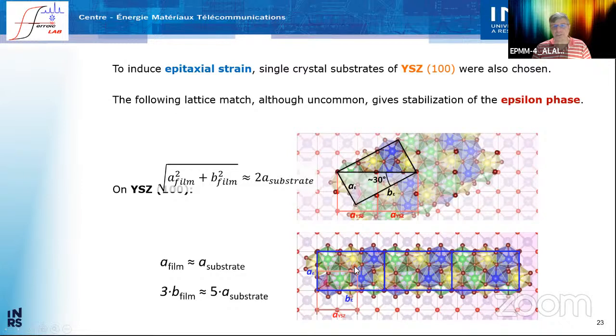And these epitaxial relationships have been found by actually providing the best continuity of the oxygen sublattice between epsilon ferrite and the substrate. Why is it interesting to have it on YSZ 100? Because YSZ 100 can be very easily grown on silicon. Therefore, those thin films, potentially multiferroic, could be grown on silicon, with a silicon compatible technology.